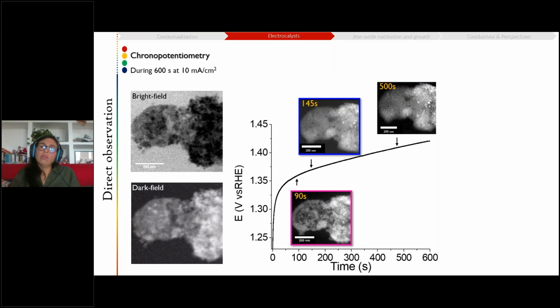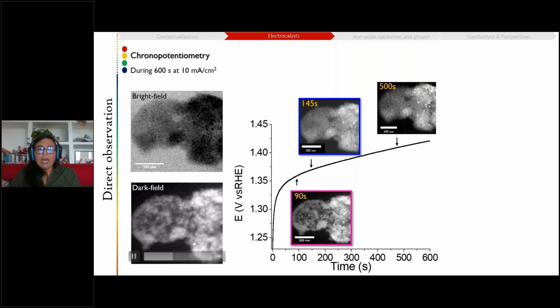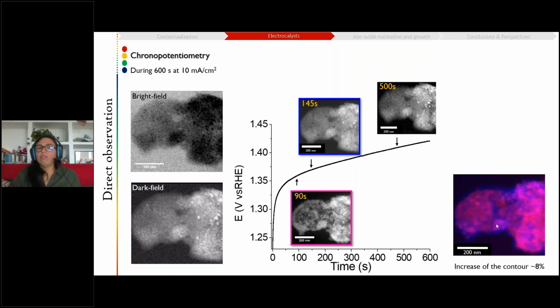Next thing that we were able to do was to test how far this amorphization can go. To do so, instead of cycling the potential, we fix a certain current and we observe how the potential changes and what is happening on our material while this is happening. So we see our particles changing in form. This overall mushroom, I will repeat it, increases in size, and the most contrasted parts mean that they are crystalline particles, and the rest of it becomes amorphous. The overall change of this agglomerate is an increase of the size of around 8%, which means that the amorphous layer, of course, takes more space than the crystalline part.